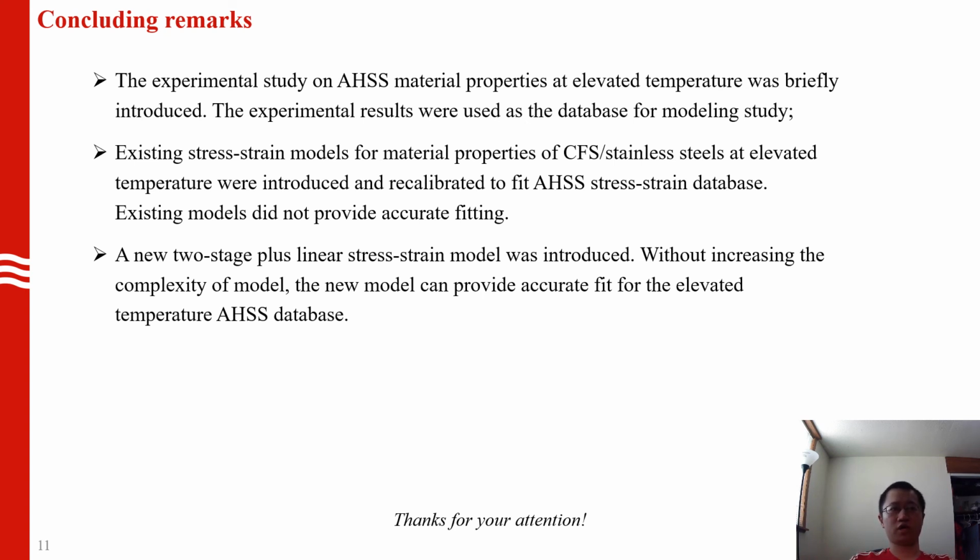And for the modeling study, first of all, we tried to use the existing stress-strain models for cold-formed steel and stainless steel at elevated temperature, and we recalibrated all these models to fit our AHSS database. Unfortunately, these existing models cannot provide an accurate fit for our database.